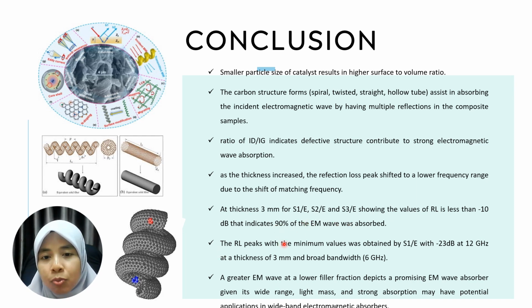The RL peak with the minimum value was obtained by S1E at negative 23 dB, for thickness 3 mm and with a broad bandwidth of 6 GHz. So a great EM wave absorption at a lower thickness depicts a promising EM wave absorber at a wide range with light mass and strong absorption, and it may have potential application to be used as an electromagnetic absorbent.